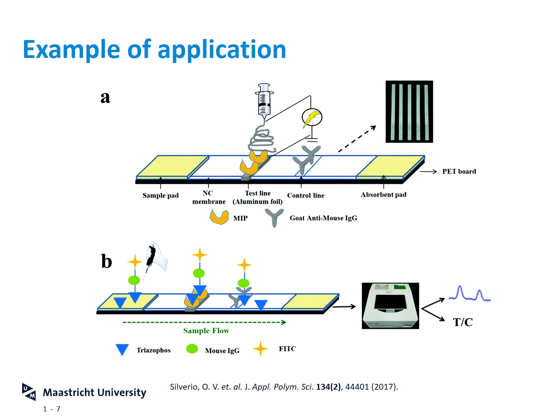And the more pesticide you have in your sample, the less conjugate, so the less FITC, is able to bind at the test line. So you will get a weaker signal at the test line. Your control line will stay the same, and the weaker the signal is at the test line, the more pesticide is present in your environmental sample. And they actually use this to determine pesticide contamination in wastewater